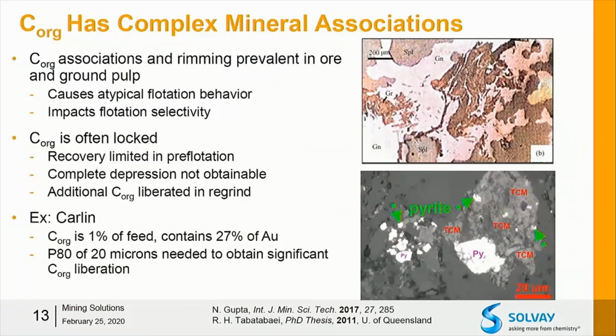Okay, and the last thing is mineral associations. And I think this is, to me, by far the most important and complex factor that really needs to be understood with carbon. The mineralogy tends to be intimately associated with values and with gangue minerals. And understanding this has a lot to do with the actual flotation selectivity that you see when you process a carbonaceous ore. It tends to lead to very atypical flotation behavior, where, say, pyrite will not be depressed with cyanide,